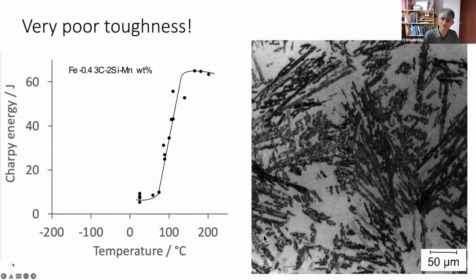Okay, that's important. What's happening is that the T0 curve prevents large regions of carbon-enriched austenite from transforming. The reaction will simply stop, and there's nothing you can do about that. So you're left with these large blocks of austenite rather than the nice thin films in between. And those transform under the influence of a small stress to untempered high carbon martensite. So it's like designing a beautiful structure, but throwing bricks of the size of 50 micrometers inside your structure. So what can we do about this?